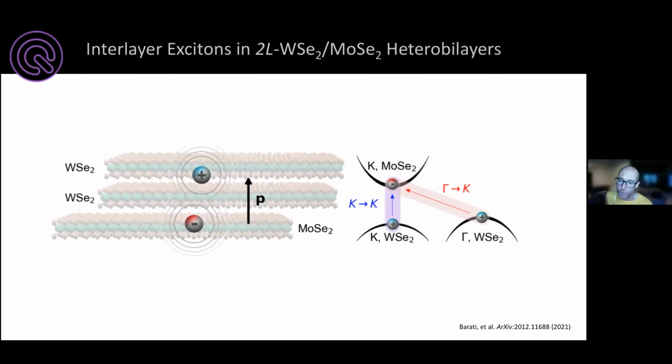And what we understand about these excitons is that they come from basically 2 different lowest lying states, but we're doing photocurrent. And so photocurrent essentially probes absorption. So whereas you may not see such strong features like this in, say, a PL measurement, we're probing directly the absorption. And so we can see both the absorption of what is called the KK interlayer exciton, but also a gamma K interlayer exciton. But on top of that, we're seeing these 30 millielectron volt echoes.